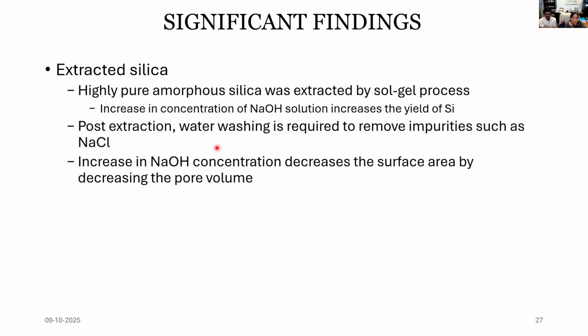And coming to the results, there are significant findings on the extracted silica. We could use a very simplified method to extract the pure amorphous silica from the system by the sol-gel process. Especially, if we increase the concentration of the sodium hydroxide, then the yield of the silica which we are extracting from the agro residue increases.